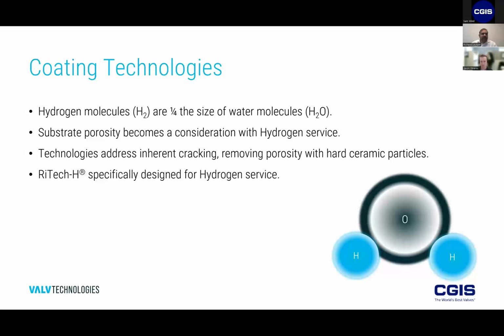So I focus on coating as a distinct difference to weld overlays. Weld overlays is where you have a high performance metal welded over a cheaper substrate, typically such as carbon steel. But a coating is not applied that way. A coating is much thinner. It's not a mechanical bond, it's actually a chemical bond. And so the way that coatings are applied, typically the term you may have heard, HVOF, so high velocity oxygen fuel. We accelerate particles supersonically. They hit a substrate at a very, very high force, and that creates a bond. The higher that force is applied, the stronger that bond is.